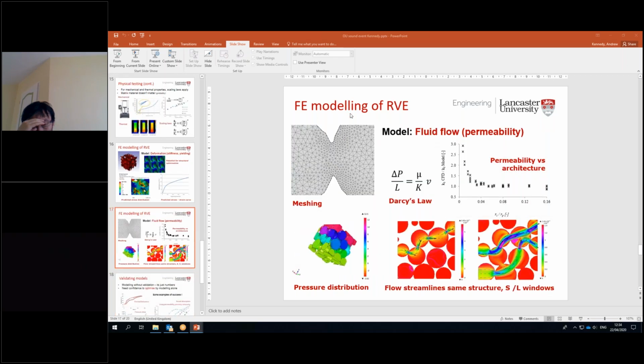Similarly, there's good modeling to be done on fluid flow, obviously meshing the inverse of our structure, the gaps between the material. And again, looking at pressure distributions to integrate with things like Darcy's law to look at the permeability, and looking very keenly at the changes in permeability as a function of architecture. So at the bottom, we show flow streamlines, and we can get pressure drops from the same analysis or similar analyses as a function of the level of connectivity between the structures. So the size of the gaps between the spheres, and we can look at local perturbations in flow, and we can look at more global effects on the pressure drop and the permeability of the system.